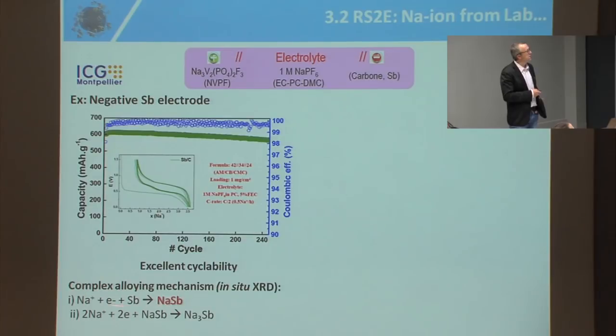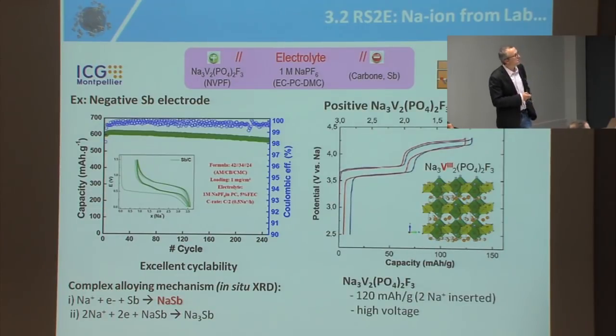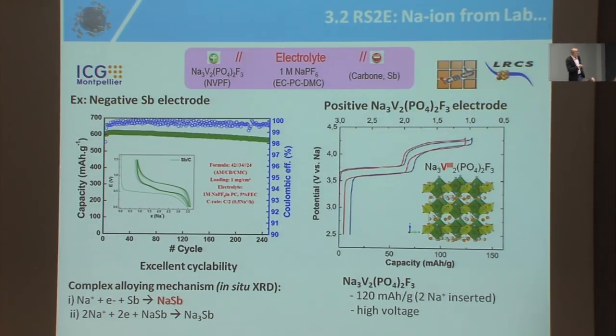When you take antimony electrode, this is alloying reaction. You remember alloying reaction? Surprisingly, in sodium, it works very nicely. You have here capacity versus cycle number, 600 milliampere hour per gram, 250 cycles, very nice. On the positive electrode, we have designed a new material, a new structure of an old-fashioned material, NVPF. It works. This is the charge here, the discharge. Potential versus time. It works very nicely.